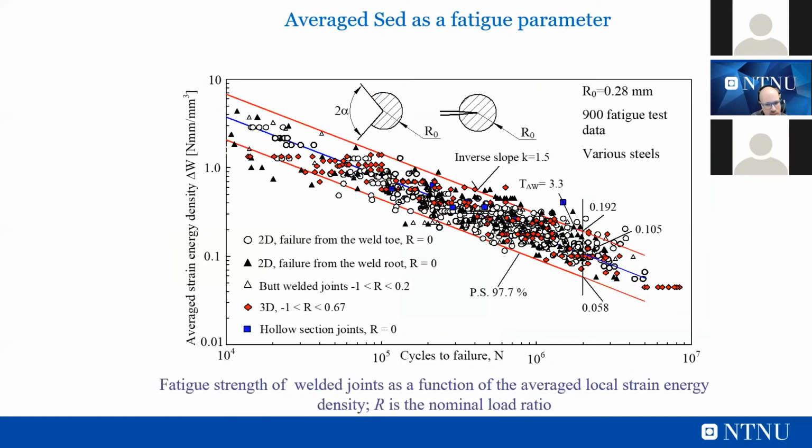And this is the curve that we plotted together with Lazzarin, reported in several papers later, because this is the standard curve and our master curve for design that we reused many times in our academic life as a benchmark for different applications. What is interesting to note is that this scatter band is nowadays updated. In the first version it included 900 data, but nowadays it includes more than 3000 data taken from the literature, following the new trends and developments. So it's quite an updated curve.